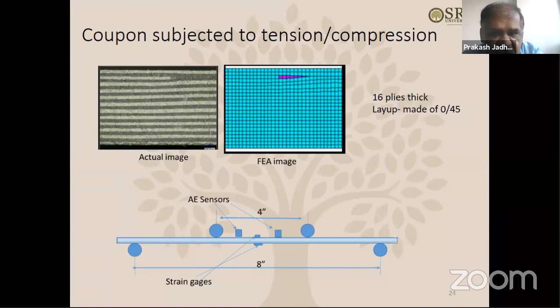So that's what will tell us how much effect the presence of ply drop has near the tensile surface or the compressive surface. So this is basically to evaluate the ply drops under tension compression. So here again, 16 plies thick plies were used, and they were made of 0 and 45 orientation fibers. Okay. This was for the tension compressions, like ply drop, which is subjected to tensile and compressive loading.